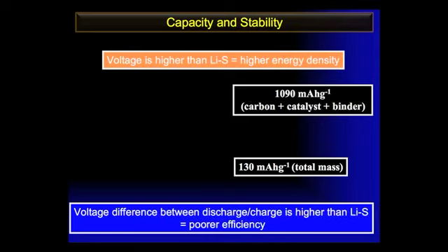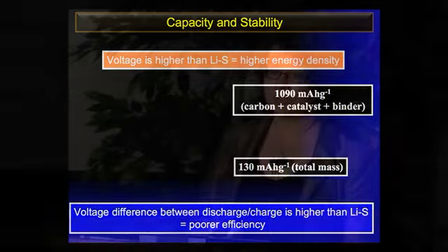So we're able to get to fairly high capacities in these systems, approaching 1090 milliamp hours per gram. And we've lowered the charge potential to 3.85 volts. And we know we form peroxide because the XRD shows that clearly. And the most hopeful side of this is that we can cycle the cell. Now, this is only 4 cycles, and I appreciate that this is only a tiny step, but compared to alpha MnO2 or no catalyst, we are at least able to sustain this, even increase the capacity a little bit on the 3rd cycle to, as I said, reasonable levels.